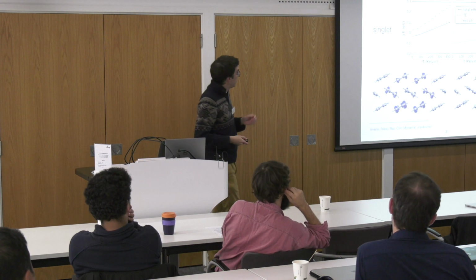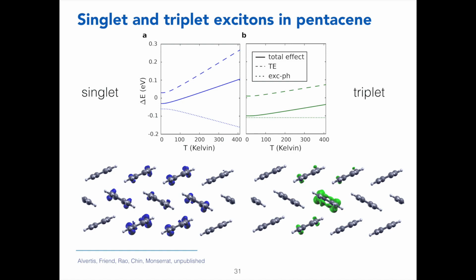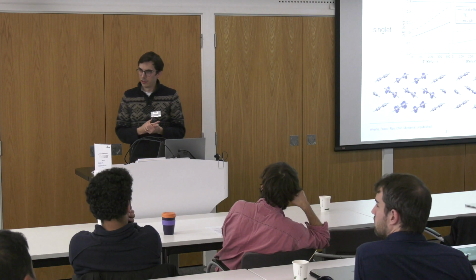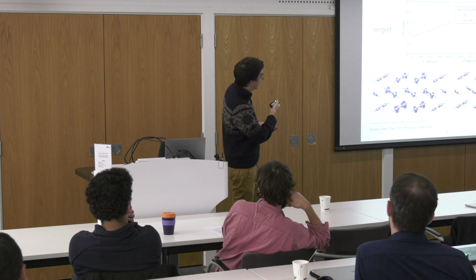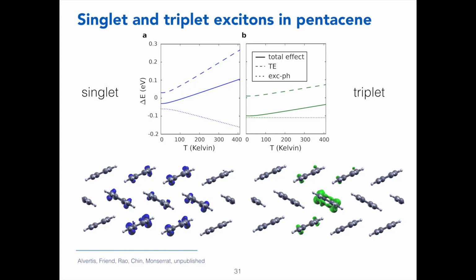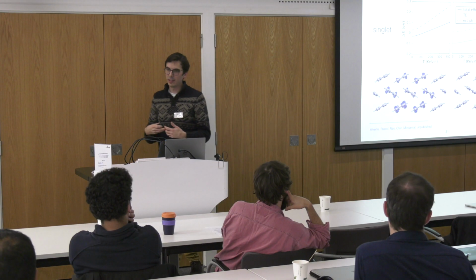So we're looking at the canonical organic semiconductor, which has featured many, many times today already, which is pentacene. And down here I have two pictures of the structure of pentacene, where I draw the exciton wave functions, in particular the singlet exciton wave function and the triplet exciton wave function. What I want you to notice is that the triplet exciton wave function is pretty much localized around a single pentacene molecule, whereas the singlet exciton wave function spans a number of molecules. So the localization character of these excitons is very different.